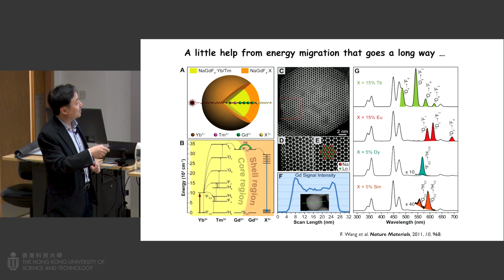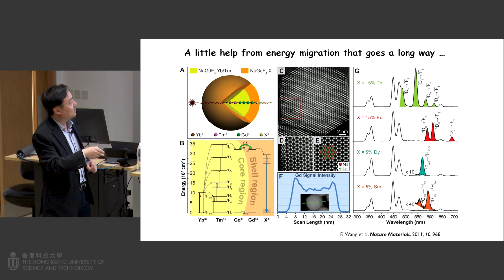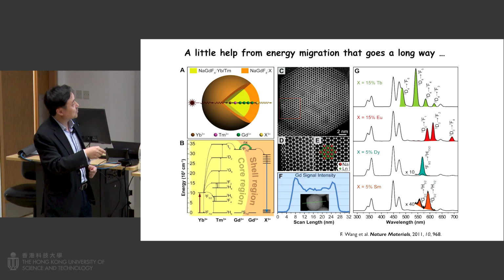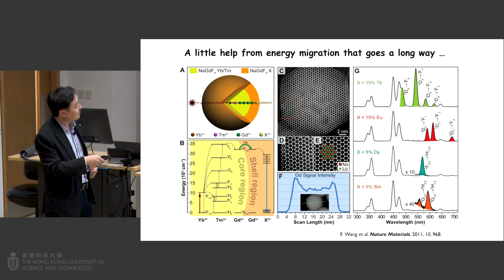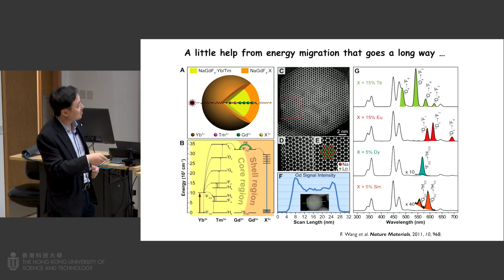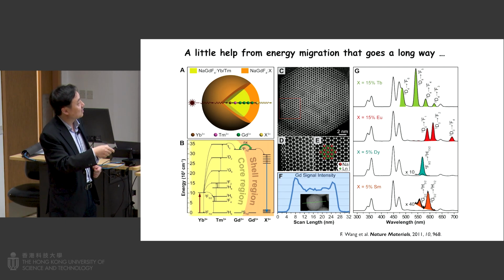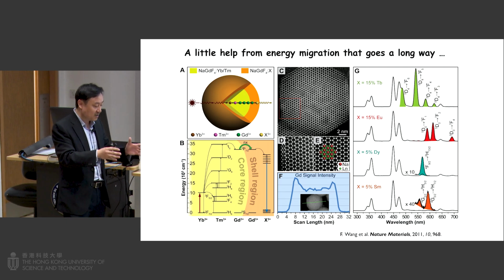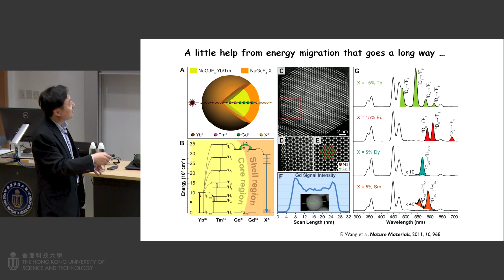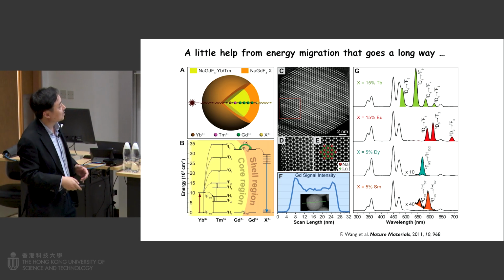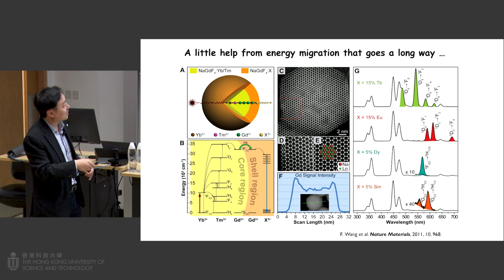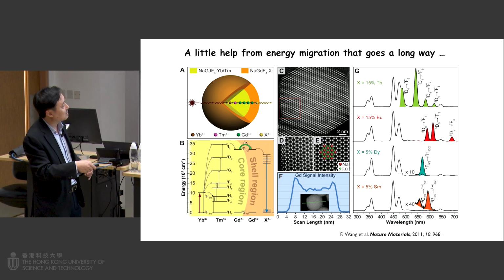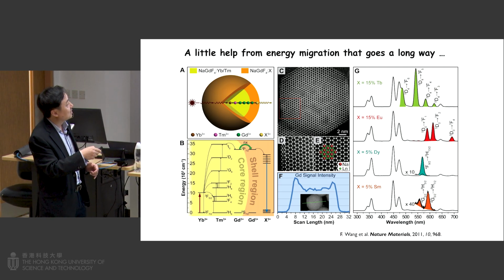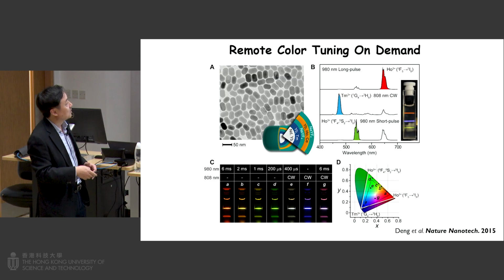If we try to identify the core-shell structure, this is a very good high-resolution TEM image. We can even see the sodium ion, this little spot right here. But we cannot see the core-shell interface because lanthanide ions have very similar ionic radius, so you essentially don't see anything here. But using elemental mapping, we can clearly see these are core-shell structures.